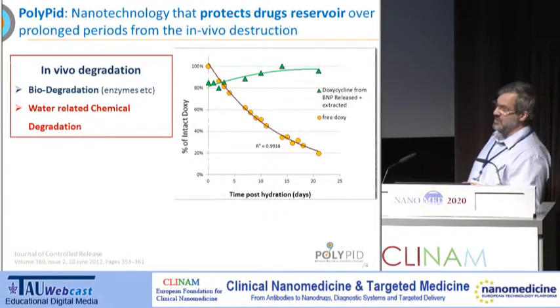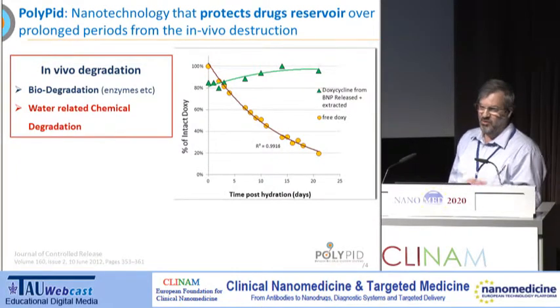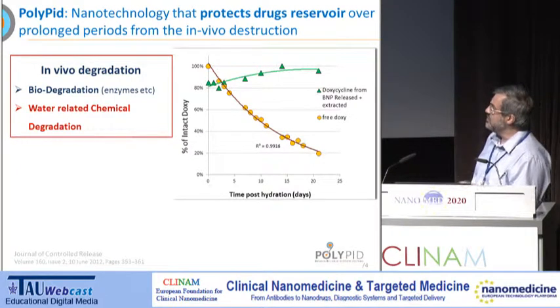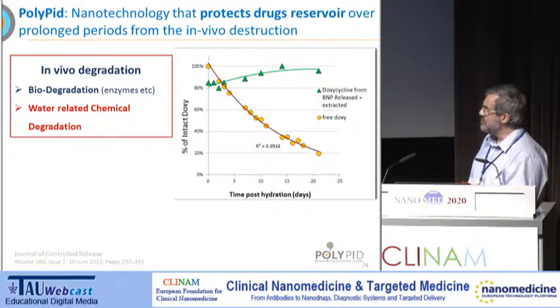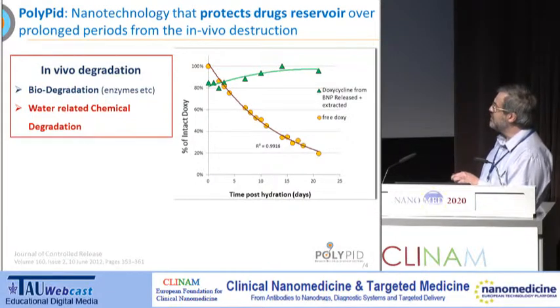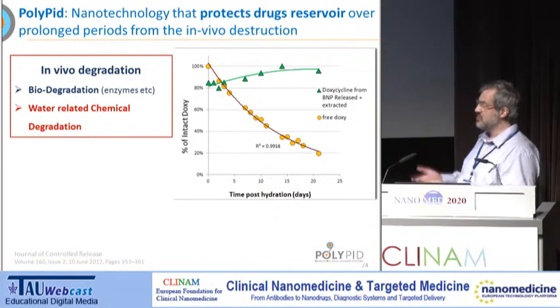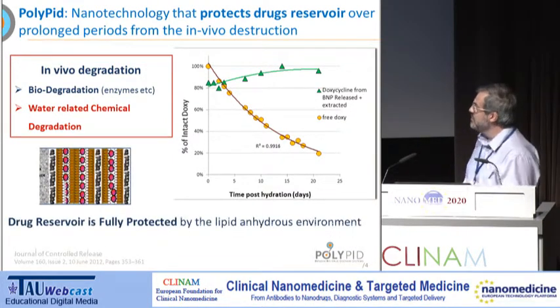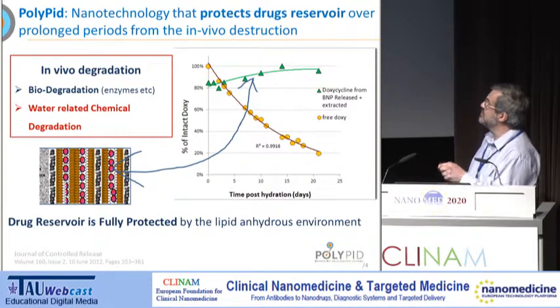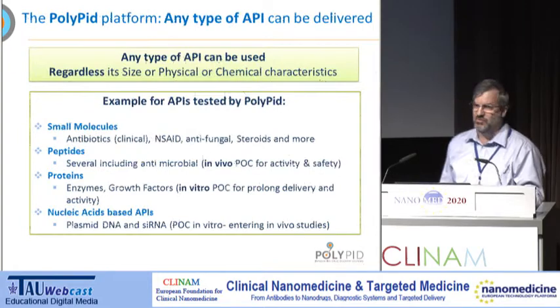Another important aspect is to protect the drug reservoir locally in vivo. If you want prolonged duration, you have to consider degradation — either biodegradation by enzymes or water-related degradation. With doxycycline, an antibiotic, three weeks after exposure to water you have about 20% of the drug remaining, so your drug reservoir can be lost. But in our system, the drug is fully protected within the lipid layer and therefore not exposed to hydration — there is no degradation between the layers.